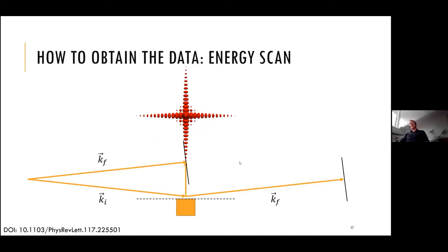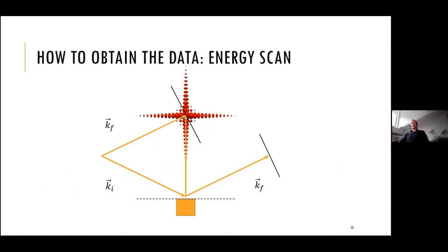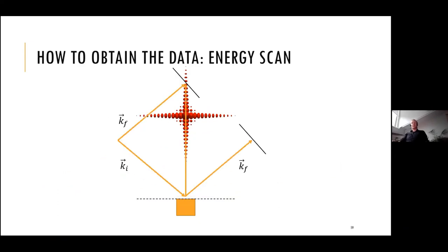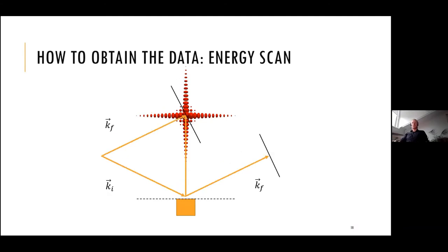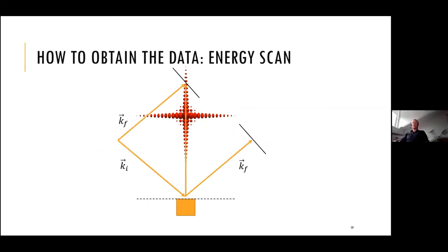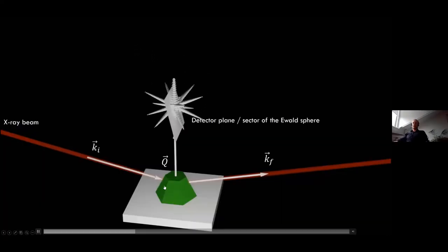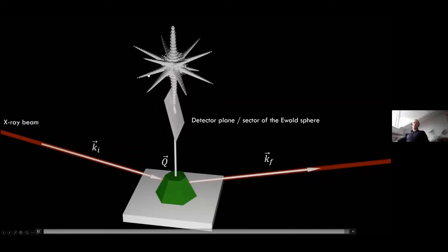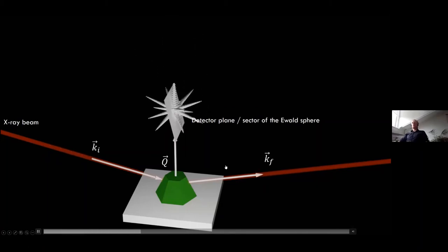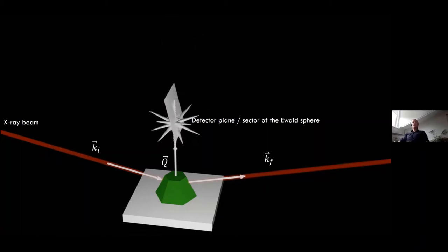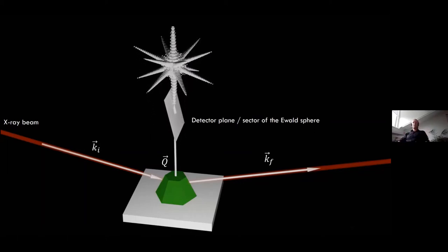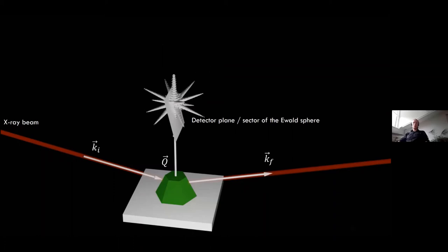You can just scan a very narrow energy range of your incoming X-rays, and basically by changing the length and the angle, this is exaggerated, you can also scan through the reciprocal space and get your three-dimensional data set. And this basically looks like that. So the lengths of the K vectors change and the resulting Q vector lengths also change. So you can map the whole 3D distribution of intensity through your detector again. However, the sampling issues or working with the data is a bit more complicated, but it's a topic for a separate talk, I guess.